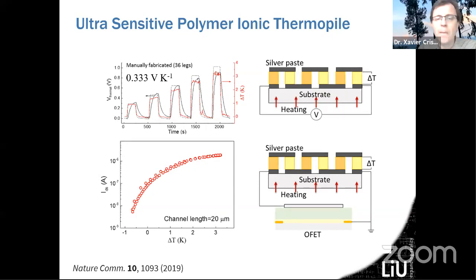Now you can even amplify further the signal, because with this kind of large voltage obtained for just a few Kelvin, you can actually switch a transistor completely. We make transistors based on electrolytes that shift at 1 or 2 volts. When you couple this sensor thermopile to a transistor, you can completely switch the transistor from off to on just by the temperature gradient, the thermovoltage basically. This gives a smart pixel for sensors using this kind of concept for very accurate temperature sensor reading.